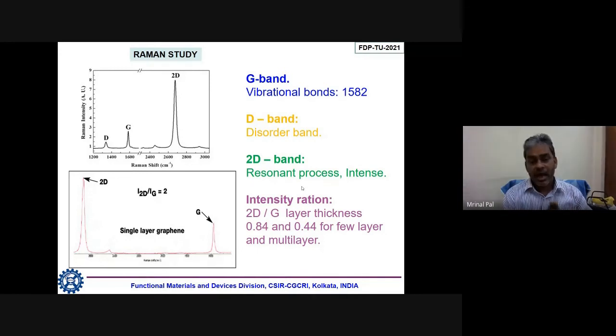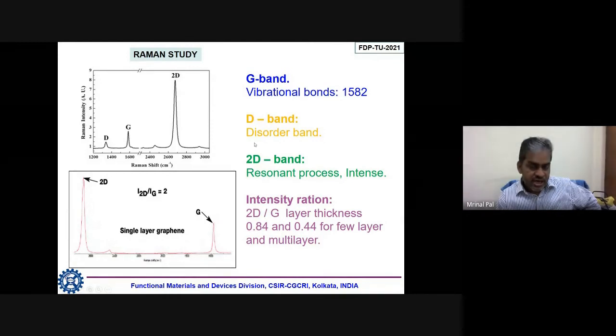defects. And why I am talking about this 2D band is because the intensity matters for graphene in case of Raman study. The ratio of the intensity of the 2D band and G band gives you some idea about the layer thickness. As we said, theoretically graphene means a single layer, but it is very difficult to really produce this single layer. So in maximum cases, this is few layer or multi-layer. So how will that be understood?